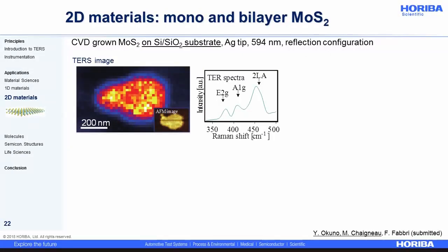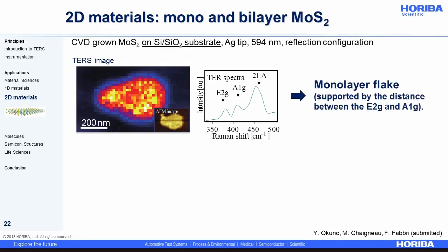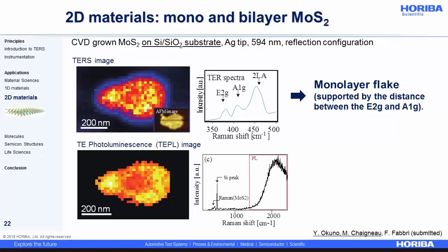Another example with the TERS map of a CVD grown molybdenum disulfide flake, here directly on a silicon dioxide substrate. So we have the first TERS image that you can see on that slide, and here the difference in the Raman shift between the E2G and A1G mode is 20 cm⁻¹. So this clearly confirms that the molybdenum disulfide flake is a single layer one. It's important to notice here on 2D TMDCs, the transition metal dichalcogenides, that not only the Raman signal is amplified, thanks to the presence of the silver-coated AFM tip, but also the